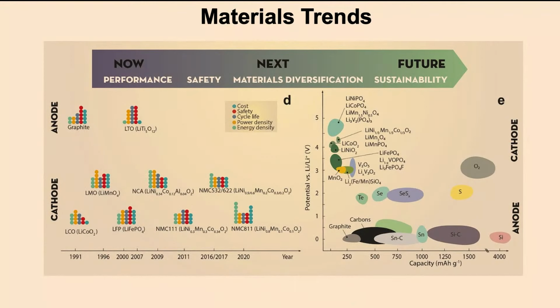Now, in lithium-ion batteries, the anode stayed pretty much constant. We're still using graphite, but the cathode changed over time from the lithium cobalt oxide to the so-called NMC materials, and I've plotted here cost, safety, cycle life, power, and energy density, so you can compare this. So basically, this shows the capacity, so the higher this value is, the better, versus the potential. You want your cathode to operate at the highest potential possible. This is a challenge because most electrolytes are not stable at these potentials, and that's why the SEI forms. But anyway, these are the material trends, and you would see that we're moving from the lithium cobalt oxide to more manganese and nickel-rich chemistries.